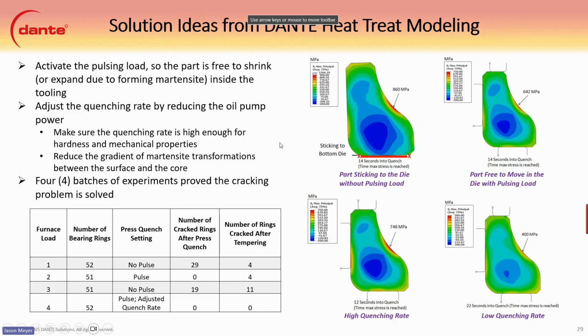The idea here was to reduce the temperature gradient, which reduces the transformation gradient between the core and the surface. So we have the 4 models here, and you can see that it's about 860 MPa in the sticking model. When the part was more free to move with the pulsing load, we reduced the tension that was being seen during the process. This one was with a higher quenching rate, and so it actually increases it compared to the pulsing load. And then the last model we did was a lower quenching rate, what we talked about, and it reduced significantly the tension that was shown on the outside edge.